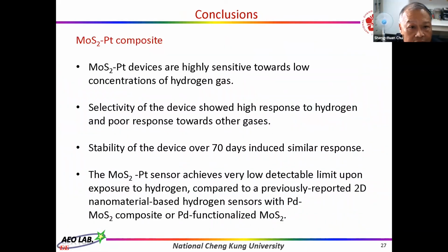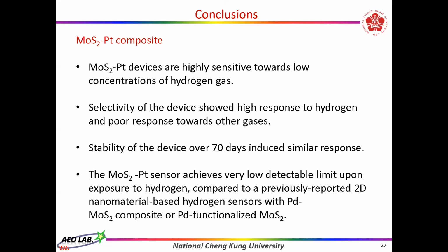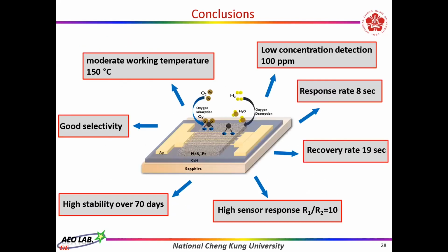Here are the conclusions. MoS2-Pt devices are highly sensitive towards low concentrations of hydrogen gas, and the device showed high response to hydrogen and poor response towards other gases, and the stability can be up to 70 days. And also, our device shows a very low detection limit upon exposure to hydrogen compared to previously reported 2D nanomaterial-based hydrogen sensors with Pd MoS2 composite or Pd functionalized MoS2. And here is the final results here.